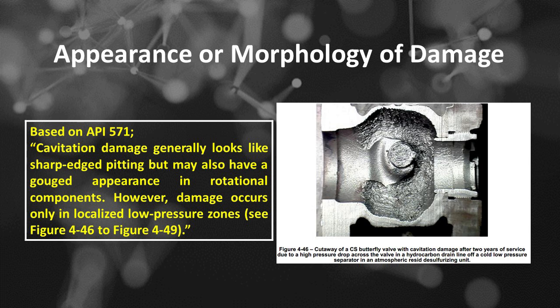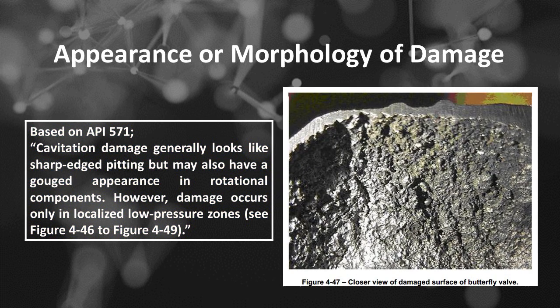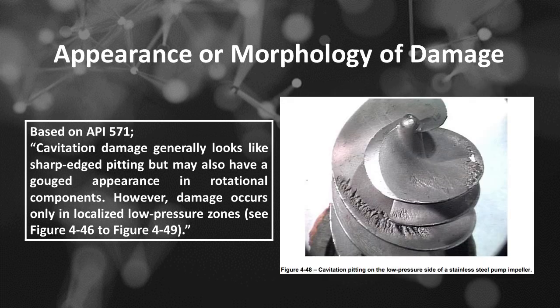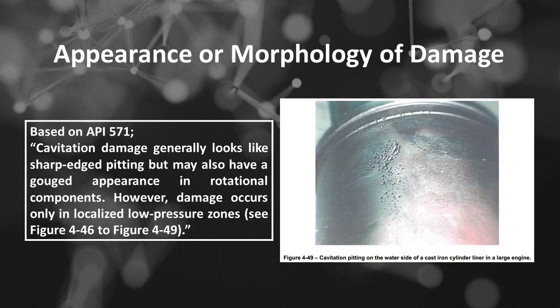Figure 4:46, cutaway of a CS butterfly valve with cavitation damage after 2 years of service due to a high-pressure drop across the valve in a hydrocarbon drain line off a cold low-pressure separator in an atmospheric resid desulfurizing unit. Figure 4:47, closer view of damaged surface of butterfly valve. Figure 4:48, cavitation pitting on the low-pressure side of a stainless steel pump impeller. Figure 4:49, cavitation pitting on the water side of a cast iron cylinder liner in a large engine.